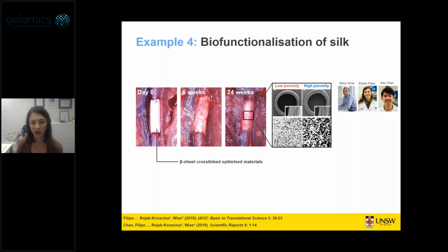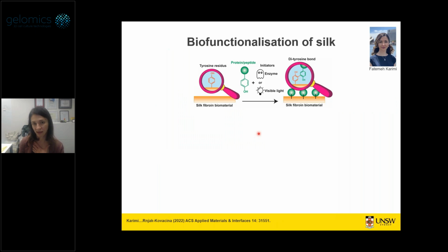And so we don't want to be changing their mechanical properties, but we might still want to be immobilizing certain proteins on the surface of these, or certain molecules. And so we think we can still use those tyrosines that are available in silk, even though it's beta sheet cross-linked, in order to immobilize another protein on the surface. And so we have shown this in another set of studies where we can now take a pre-established silk material that has these tyrosines available naturally in it, and any protein peptide that has tyrosines, and using those same chemistries I've been telling you about, you can now immobilize these molecules just on the surface of silk.